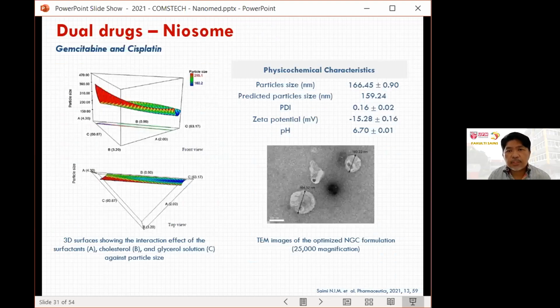Okay, so we also did other work on a dual drug, gemcitabine and cisplatin, the most common combination being used in Malaysia for the treatment. But in this case, we worked with the niosome. It's a very similar approach that we carried out. Just to highlight that based on this work, we're able to get the correct size. As we published recently, in January this year, the result also showed that the optimized niosome gemcitabine cisplatin had reduced the cytotoxicity effect against both MRC5 and A549, but in this case, of course, it is better for the A549.